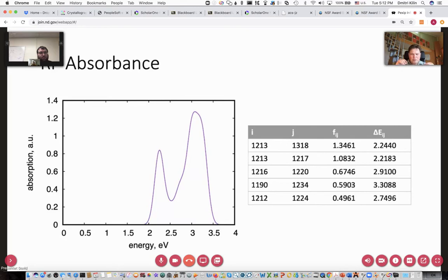There is a hypothesis that there are magic numbers, like sharing the same common denominator. So only specific combinations of number of layers will fit each other. And from what I did try myself, one needs to take into account both the thickness of the inorganic perovskite layer and the organic spacer layer and their multiplication.